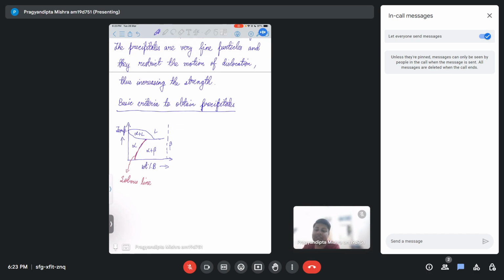So essentially the solvus line is like a minimum threshold beyond which the precipitate formation would start. This is a line which should exist for any system that we are looking at, like aluminum, copper, magnesium, zinc, etc. Only then can we say that precipitate formation would be there. Secondly, we should go from the alpha range to the alpha plus beta range, because beta is the precipitate phase. Alpha is basically the initial matrix itself. So only when we cross over to the alpha plus beta stage will we start seeing the formation of beta phase.